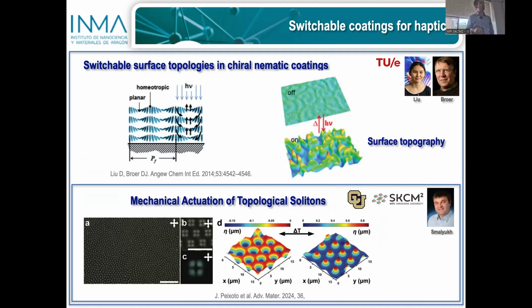Actually, very recently, published just this year, the group of Eindhoven and Ivan's group started this collaboration, in which, again, having a substrate and this type of material, it was possible to generate topological solitons, either isolated or arranged as self-assembled, solidify them with this in situ polymerization technique, go into a liquid crystal elastomer, and upon heating, you can have these large differences in the surface relief localized at the position of the solitons, having, as told, potential in optic applications. I mean, this type of protrusions can be felt with the fingers.